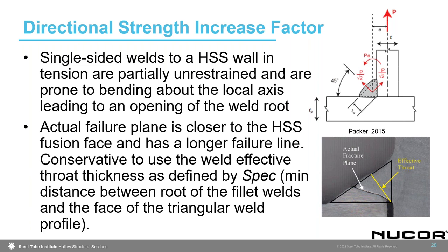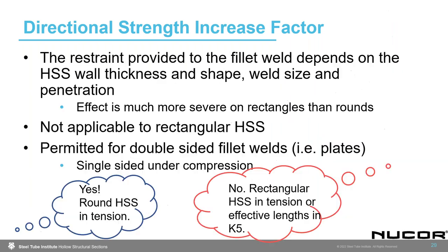When we do this, we see that the actual failure plane is closer to the HSS fusion face and has a longer failure line. So it's conservative to use the weld effective throat thickness as defined in the specification for this particular weld. The restraint that's provided to the fillet weld is going to depend on the HSS wall thickness as well as the shape, the weld size, and the penetration.